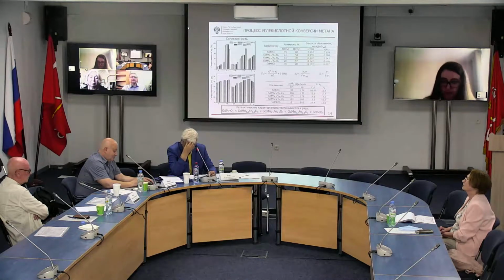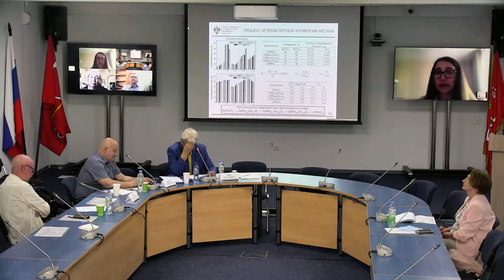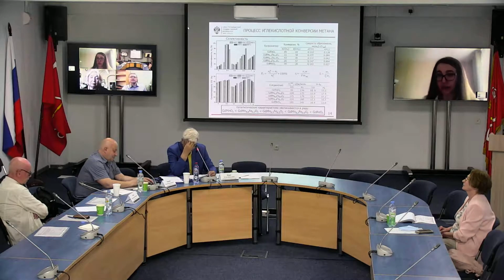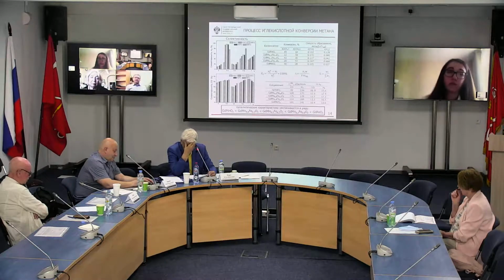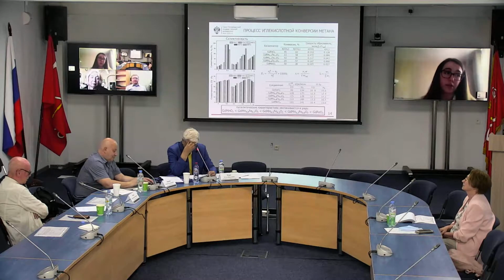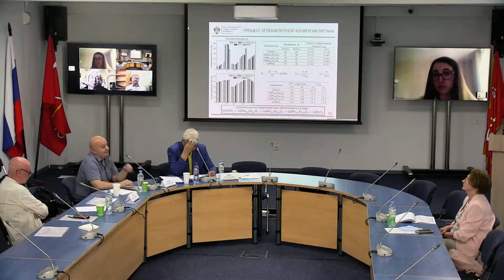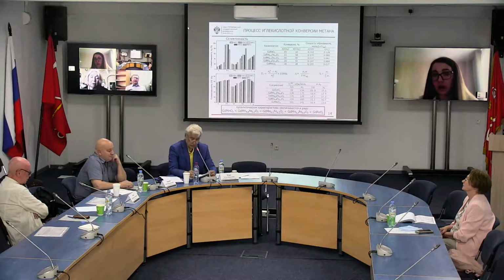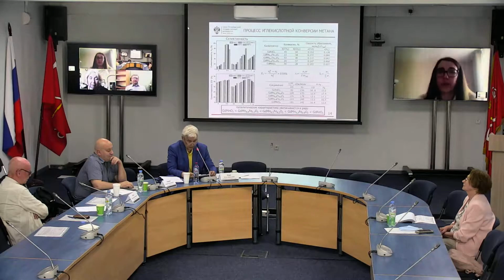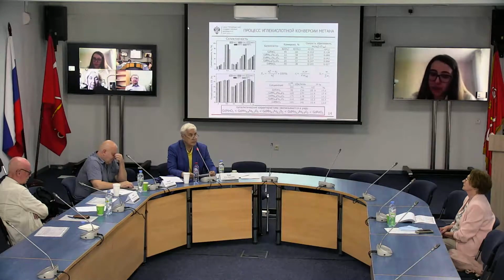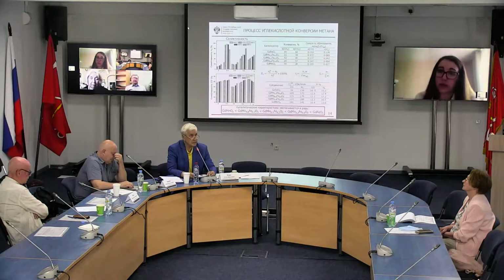Yes, we've considered this issue, and also such studies were held not just for our catalyst but also for comparison catalysts, simple oxides and silicon dioxides. We've taken this point into account and we held such studies. And what did they show? They showed that the contact time has no significant difference, but we saw the impact of preliminary treatment, and to this end we conducted studies of thermally programming reactions.